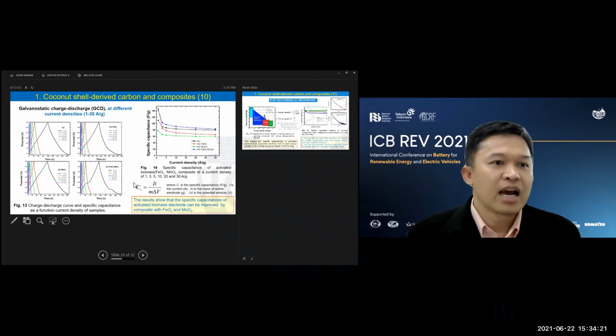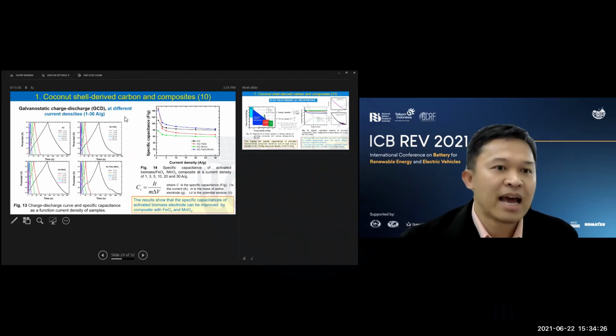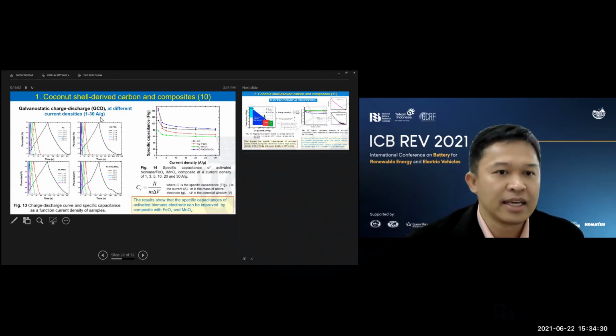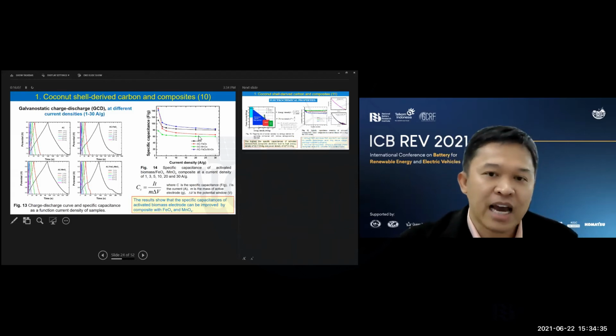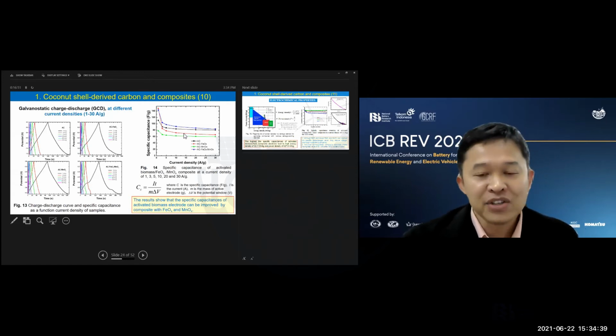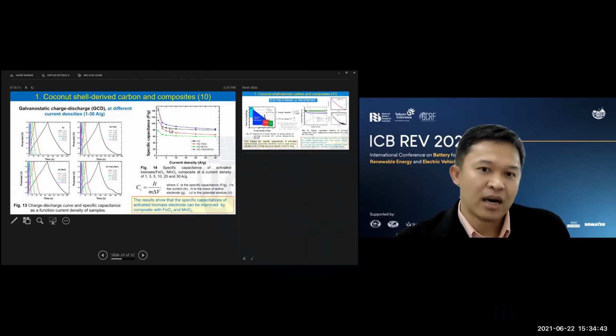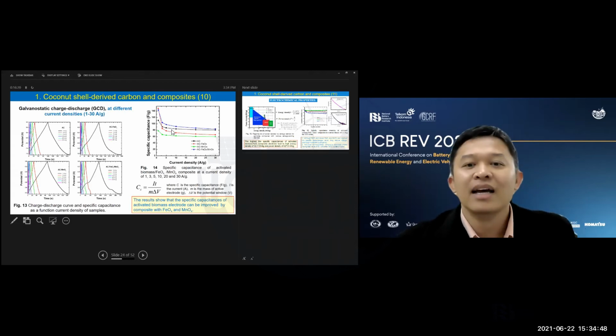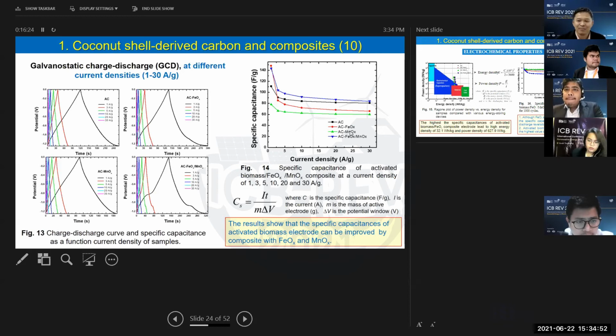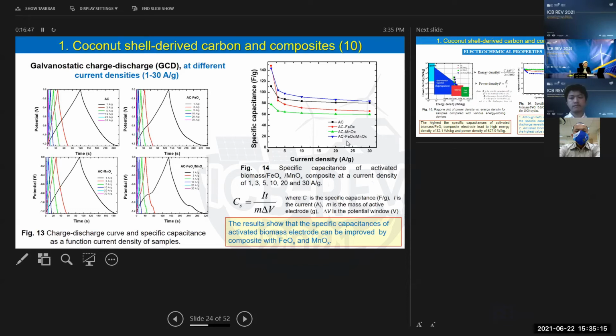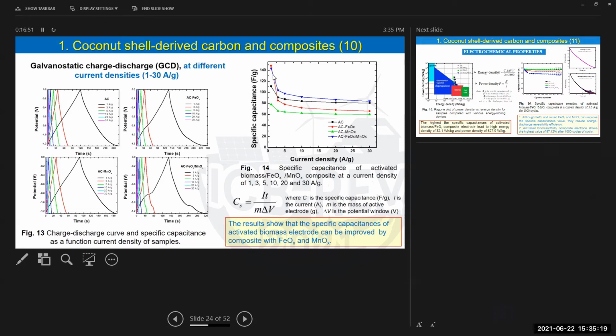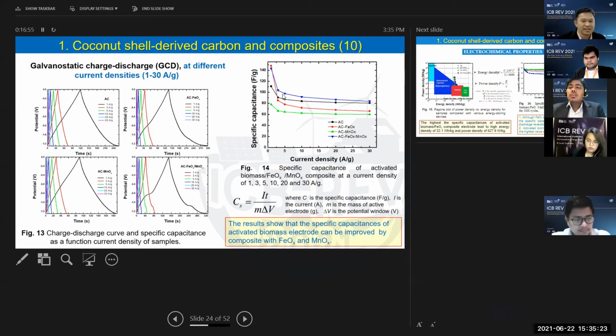We also use the galvanostatic charge-discharge technique, and we measure it at different current densities, ranging from 1 to 30 ampere per gram. The calculated specific capacitance is shown on this figure. As you can see, we can have the carbon with quite acceptable value of specific capacitance. Interestingly, for the composite with pure iron oxide and also the composite with pure manganese oxide, on the red line and also the blue line, the specific capacitance values of these composites are lower than that of the pure carbon, as shown in the black one. But for the co-composite of iron oxide and manganese oxide, we can see the improvement in the specific capacitance, as you can see on the blue line.